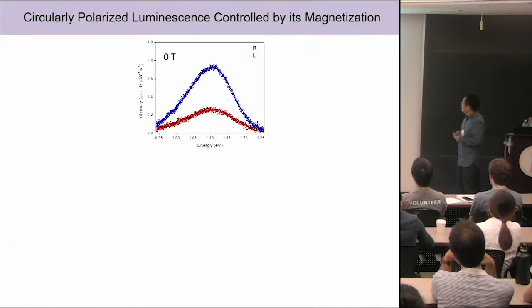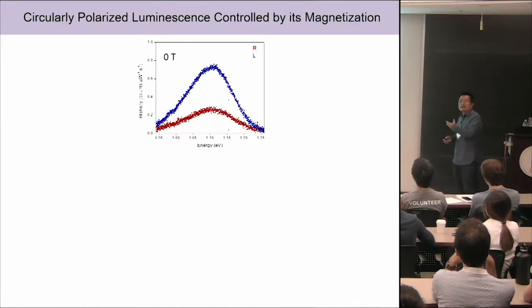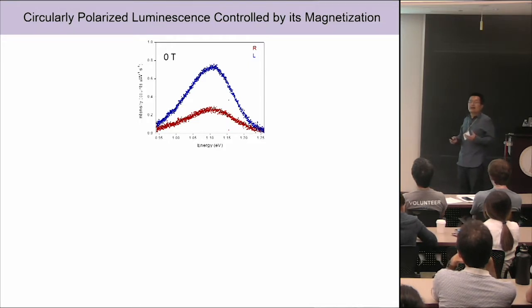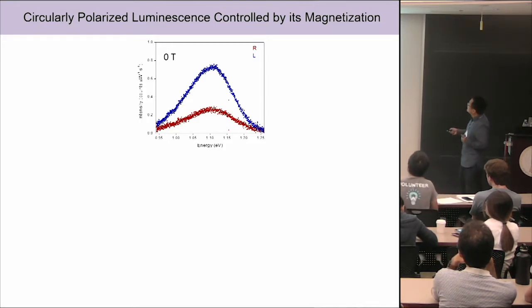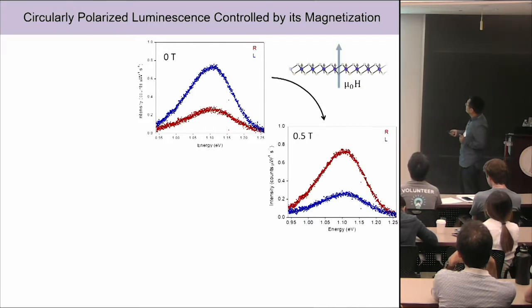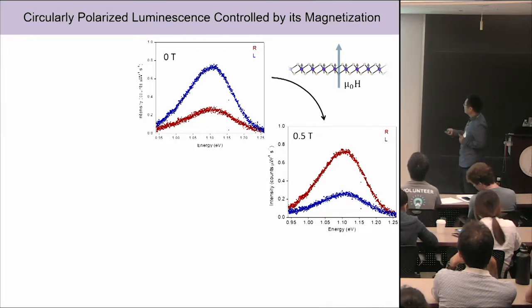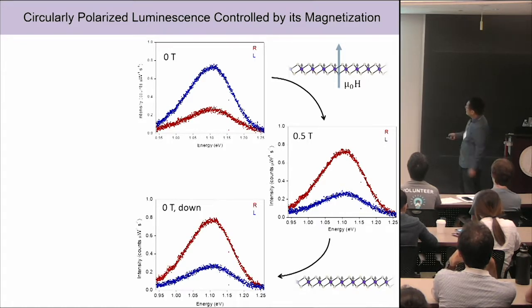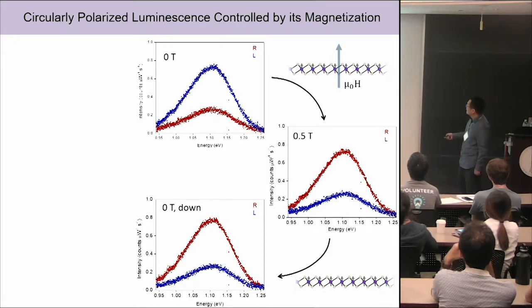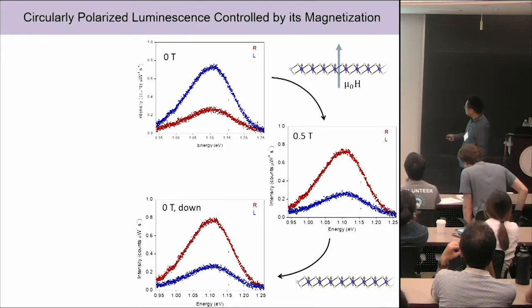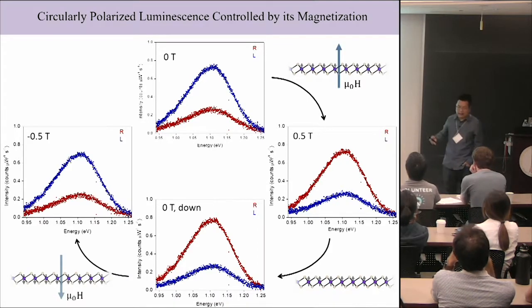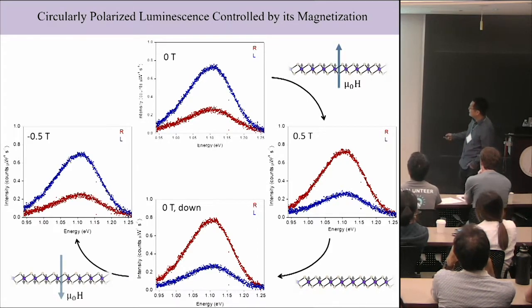Then the next thing we do is prove it is indeed coming from magnetic order. We measure the luminescence as a function of magnetic field. The top is starting from 0 Tesla. Then we increase the magnetic field and flip the magnetization to the up direction. You can see the polarization is flipped. The red is now stronger than blue. Then we go back to 0 Tesla, and because of hysteresis, the memory effect, the polarization is still red stronger. Then I apply a large enough negative field to flip the magnetization, and the circular polarization also flips.